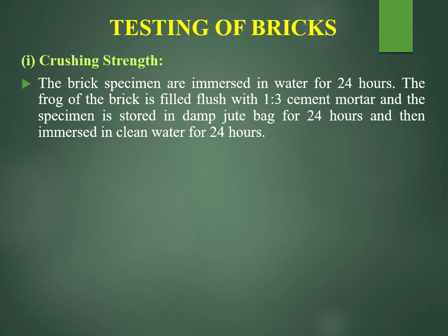After filling with the mortar, wrap the brick specimens in a jute bag, and see that this jute bag is wetted, a little damp, having moisture. Wrap the specimens in the jute bag for 24 hours, then take them out and again immerse in clean water for 24 hours.